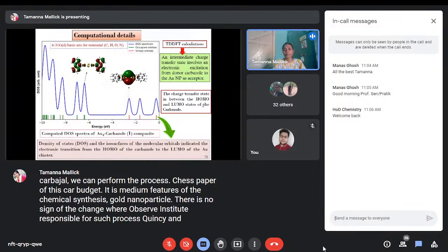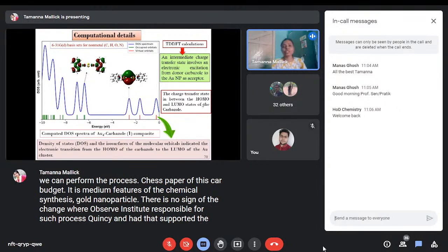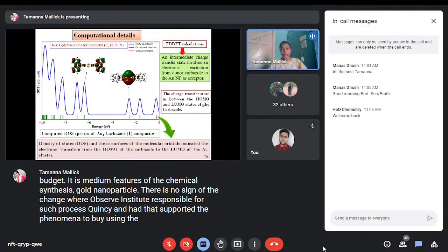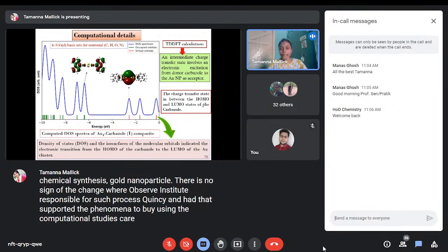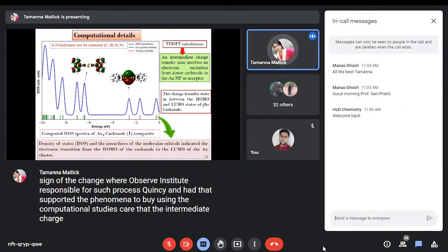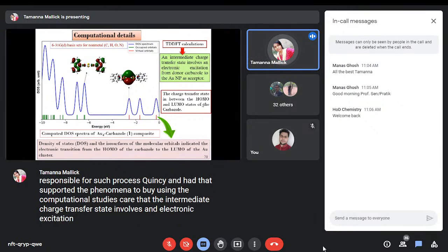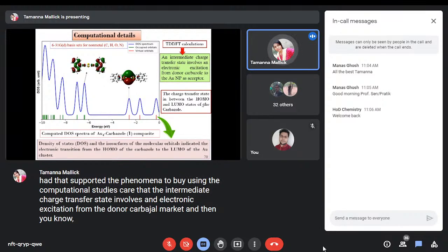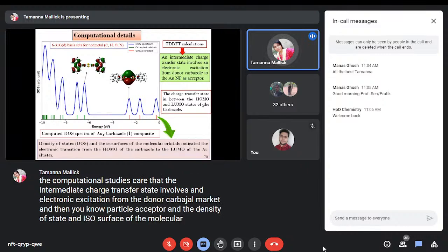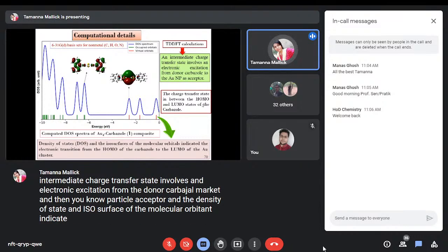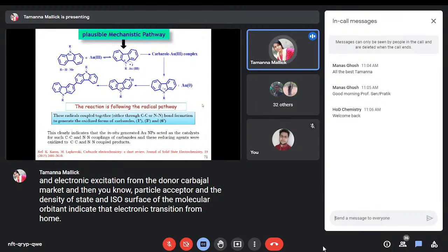This phenomenon was further supported by computational studies. Here, the intermediate charge transfer state involves an electronic excitation from the HOMO of the donor carbazole moiety to the LUMO of the Au nanoparticle acceptor. The density of states and the isosurface of the molecular orbital indicate the electronic transition from the HOMO of carbazole to the LUMO of the Au cluster. Now, this is the possible mechanistic pathway.